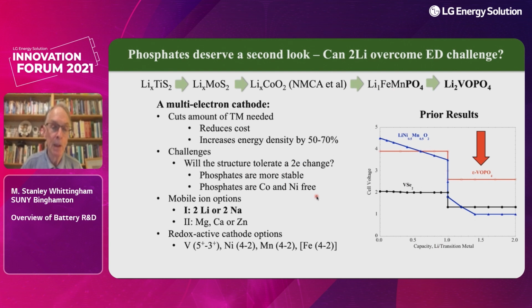On the mobile ions, we have 2 options, lithium or sodium, or we can use a divalent cation such as magnesium, calcium, or zinc. I should point out, I'm not going to discuss it, folks have looked at magnesium in these vanadium phosphates. Magnesium does not intercalate, it abstracts an oxygen and makes magnesium oxide, in our colleagues' studies.